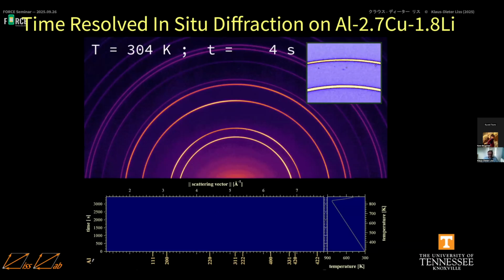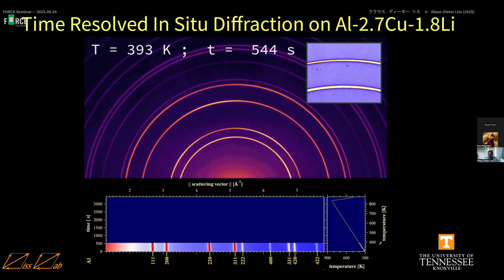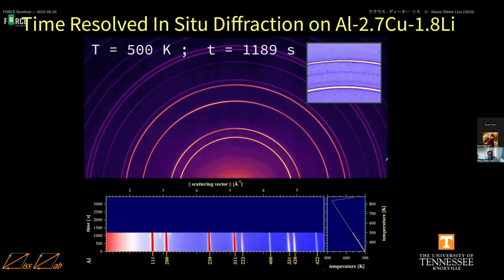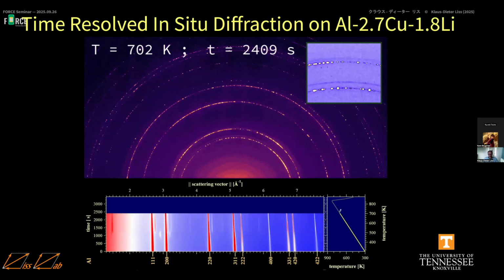So we can now look time resolved. I'm playing a movie here. We have the time here on the left, and we have the temperature on the right. We see that there's an evolution of the Debye rings. We see now that phases are coming, so there are new peaks coming, and this is due to precipitation of a phase. And what we see later on is that the first phase disappears and the other phase becomes more abundant, and eventually at very high temperature, so this is the temperature profile, it disappears as well. Now you see there's this other phase coming. This is a T1 phase, a precursor phase, and this is a T2 intermetallic in the aluminum-copper-lithium system.